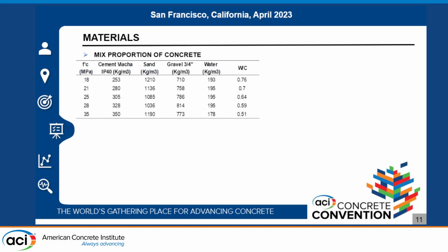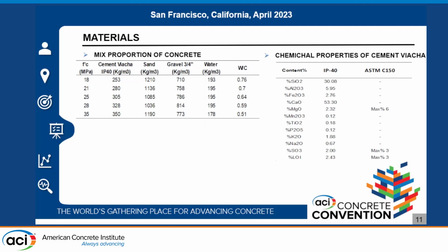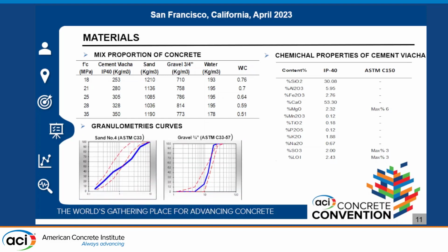Regarding the granulometric characteristics, the dosage used for each characteristic resistance reached at 28 days is presented in the next table. In the second table, we can see the composition of this IP40 cement of Viacha brand, which is under the specification of ASTM C150. And finally, the granulometric curves are within the limits established by ASTM C33.